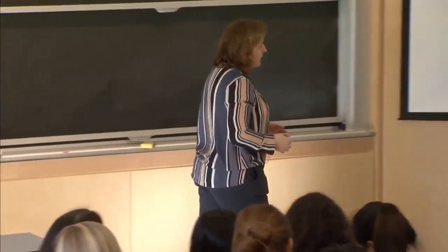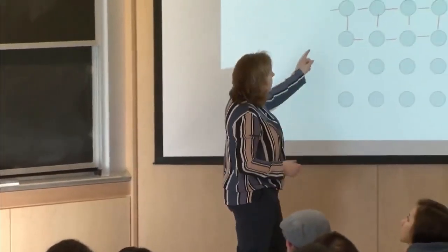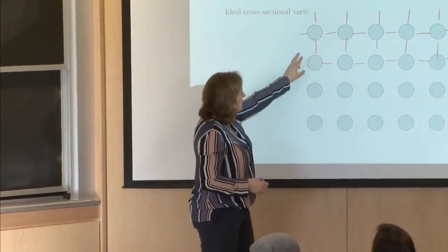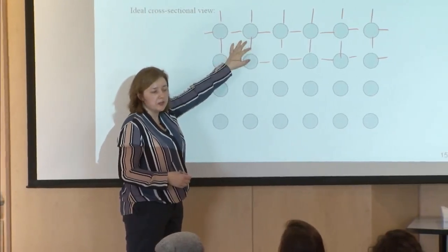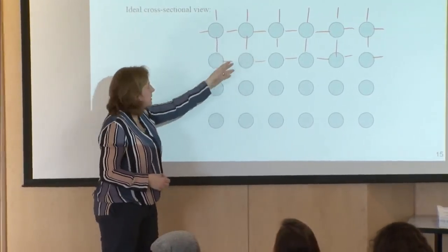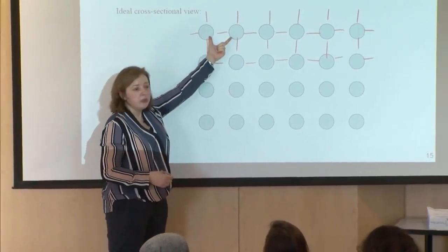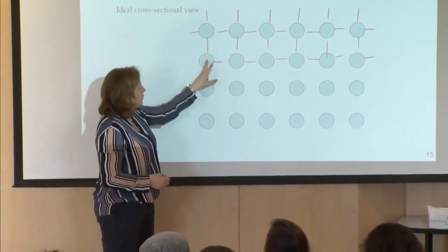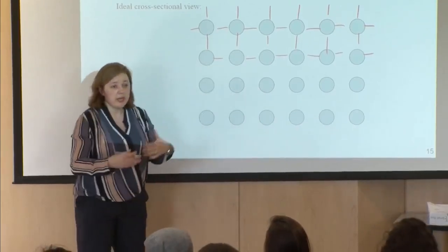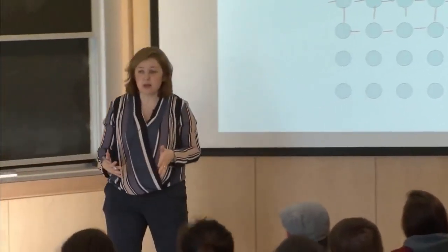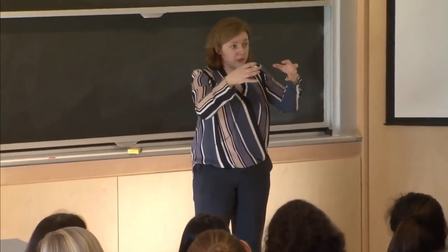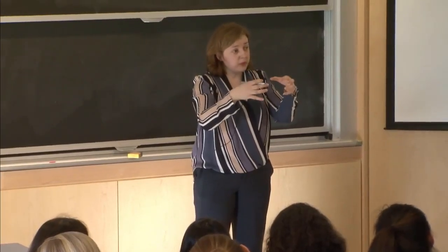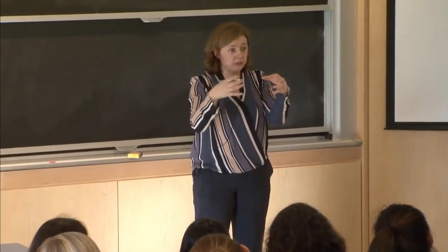And it turns out that these dangling bonds will reconstruct. What that means is that these 2 atoms will form, in this particular case, a double bond instead of a single bond. What that means is that these 2 atoms will be bonded more strongly than this atom with this atom here. So again, what is the consequence of this analysis is that their position, or their relative position within the crystal, will be different from their equilibrium position in the crystal.